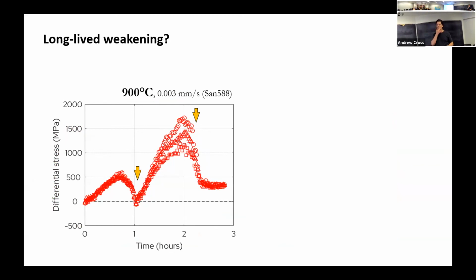This is kind of just a little aside. Something curious that we noticed, although I noticed when putting this talk together, if you compare, so we've got one of these non-hydrostatic experiments at 900 C, we're driving the rams in at 0.003 millimeters per second, which is kind of our medium strain rate. We've got our quartz that then weakens, and then we're in the coesite field here. So our coesite stresses at 900 C are around 1 to 1.5 GPa. That fits pretty well with a flow law with other experiments that people have done on coesite.